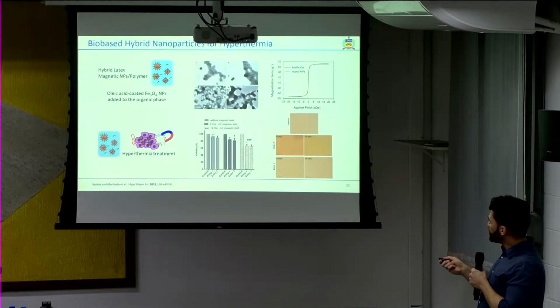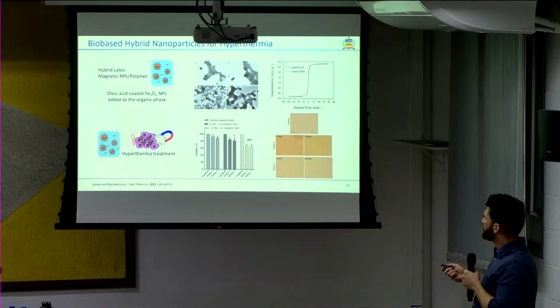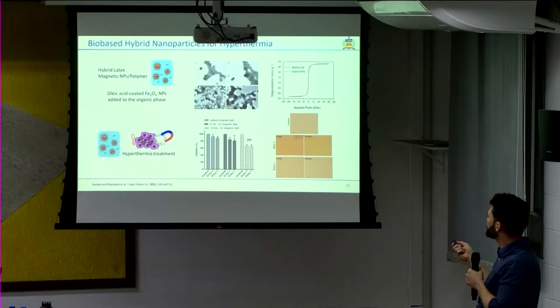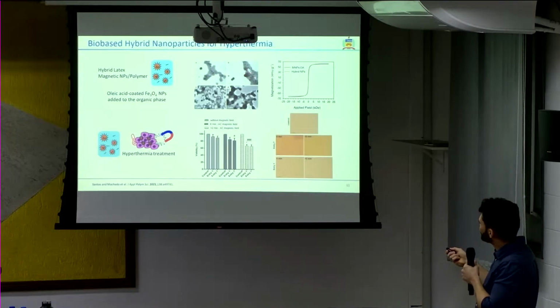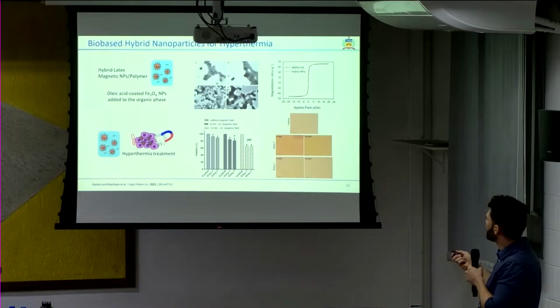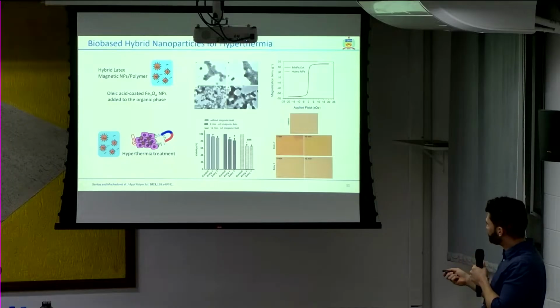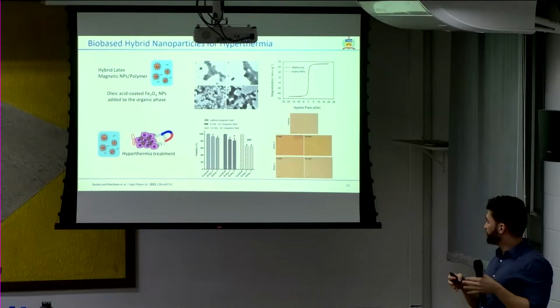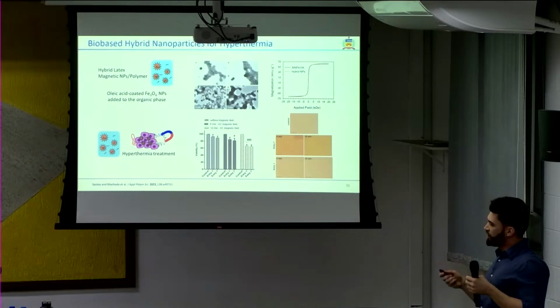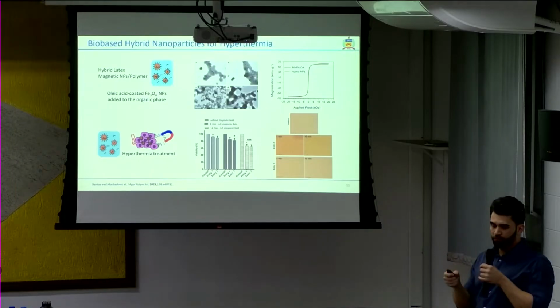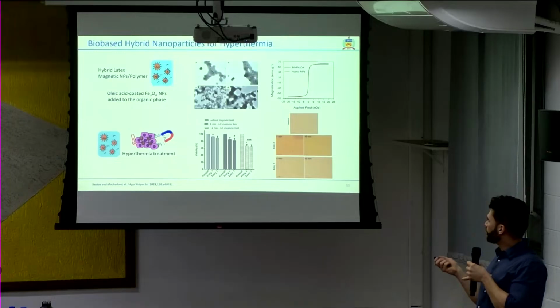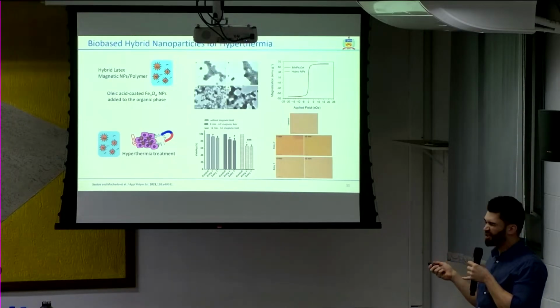And finally, we used those nanoparticles to synthesize hybrid nanoparticles for hyperthermia. So we encapsulated superparamagnetic magnetite nanoparticles. And here we can see some TEM pictures where the black dots inside the big polymer ball are the superparamagnetic magnetite. Even after encapsulation, the nanoparticles presented superparamagnetic behavior, and they were used for hyperthermia treatment, in which we applied a magnetic field to the cells with the nanoparticles intermittently, and then there would be a localized heat, and this heat would kill the cancer cells. In this case, it was HeLa cells.